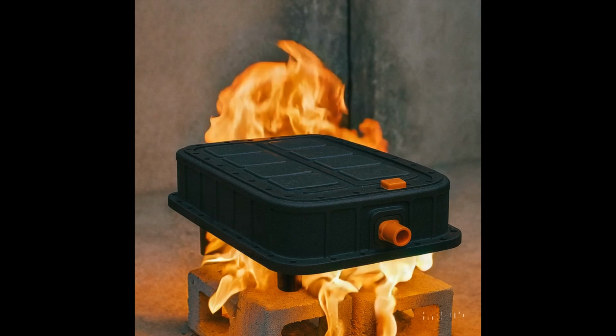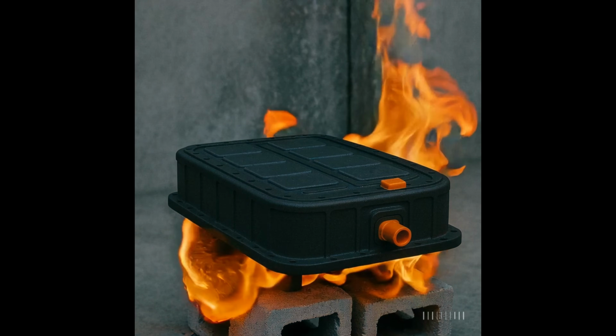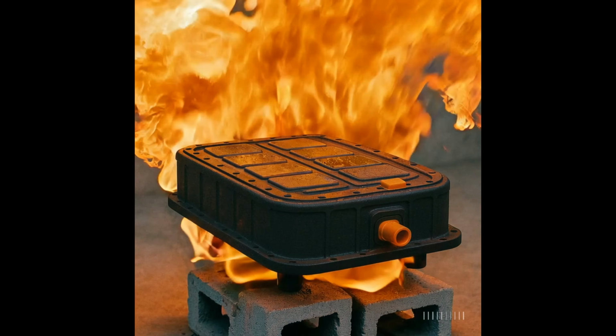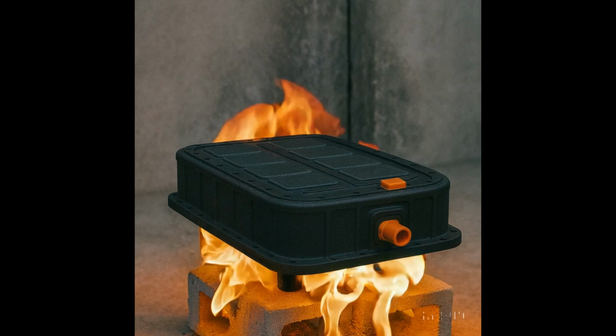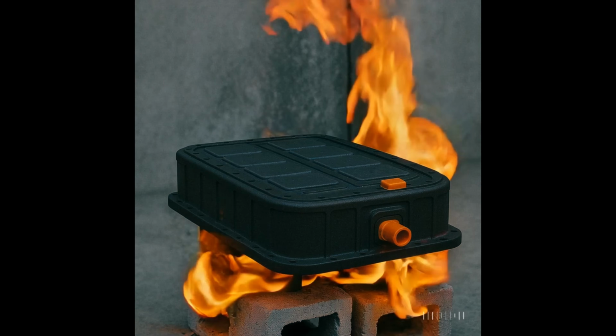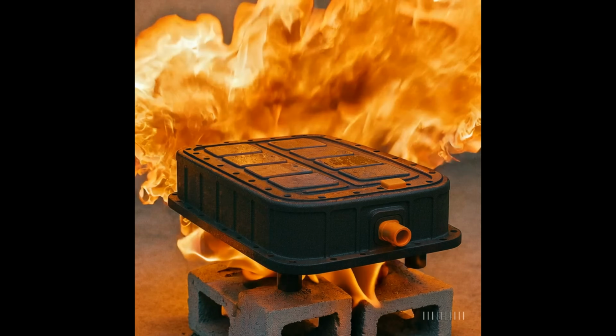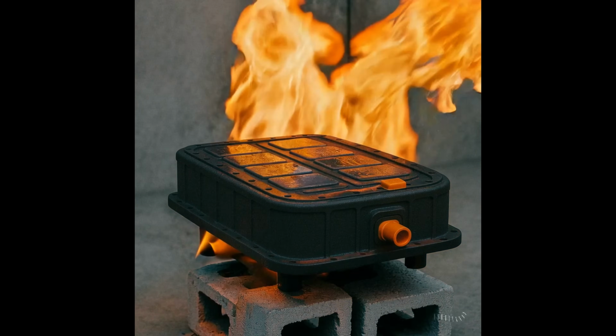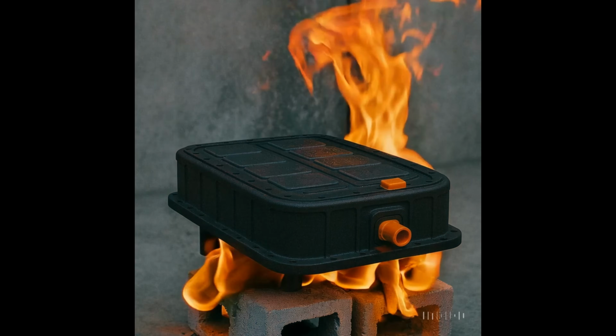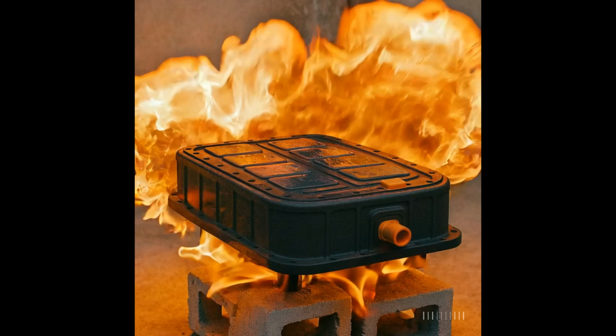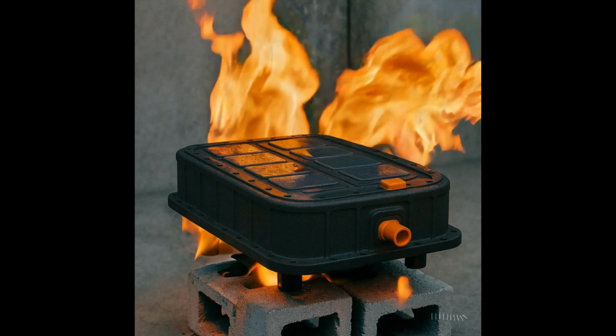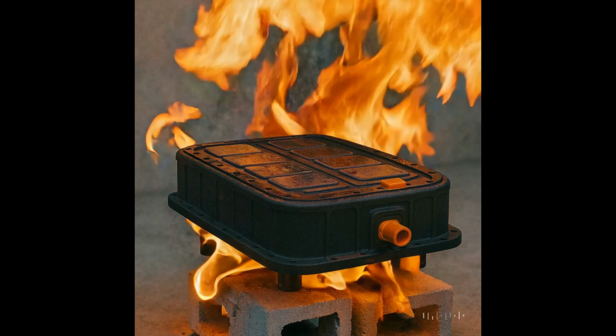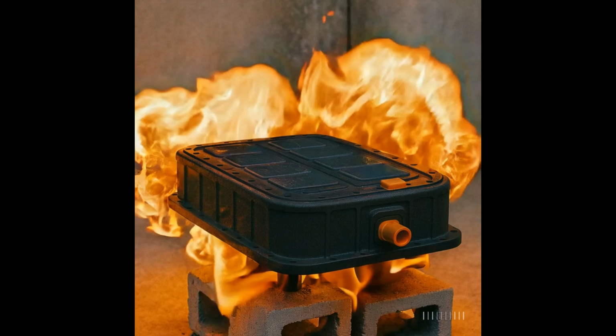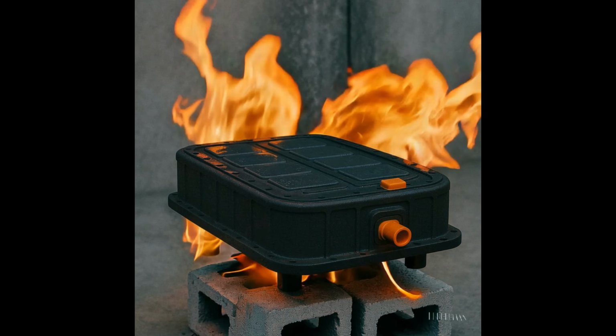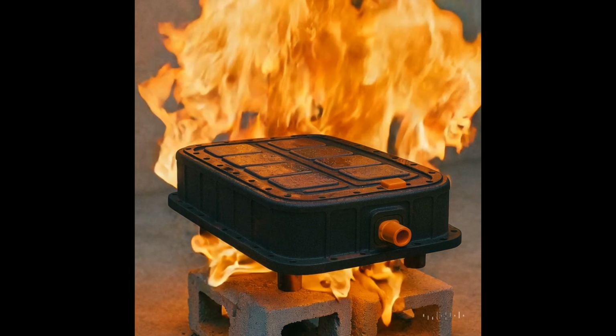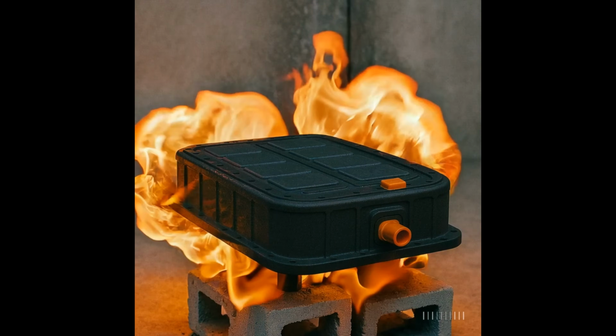However, a lot of standards include fuel fire, which is when a battery is placed over a pool fire, commonly gasoline or propane, for 70 seconds to 10 minutes, depending on pack size and standard. Typically, the flame exposure occurs horizontally or directly below the battery pack, but sometimes at an angle for corner exposure tests, depending on your requirements. Measurements include time to first cell venting, time to thermal runaway if it does occur, magnitude of explosion or flare, structural containment behavior, flame penetration into the enclosure, and post-test pack behavior. Did the safety vents function as intended, for example?